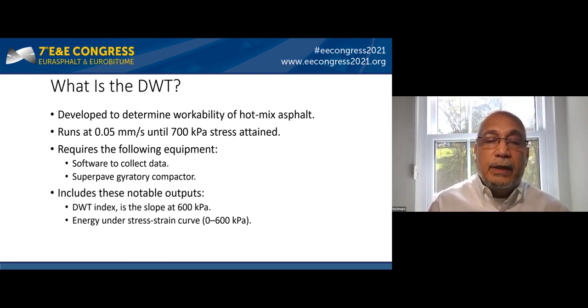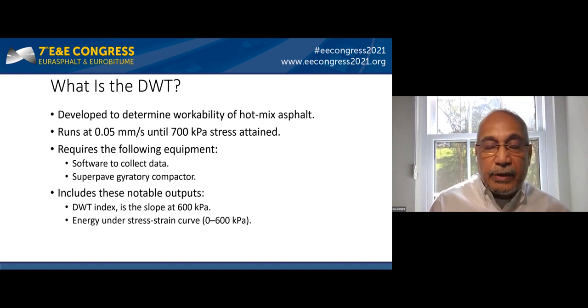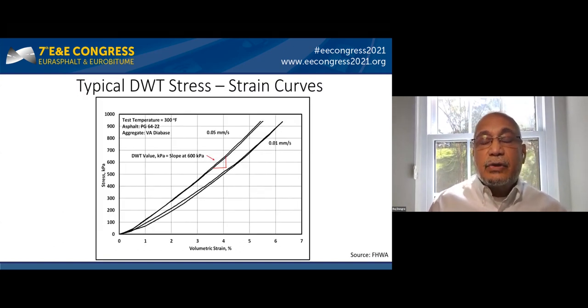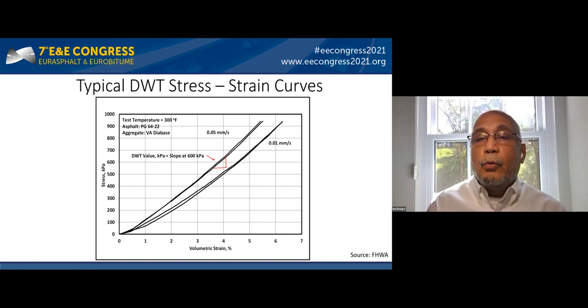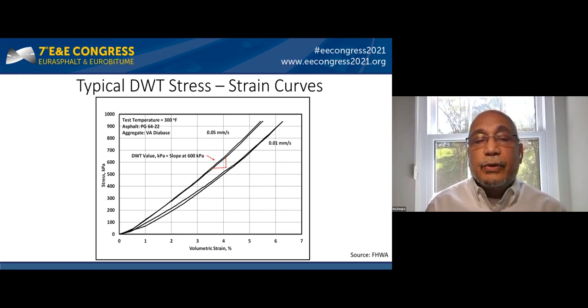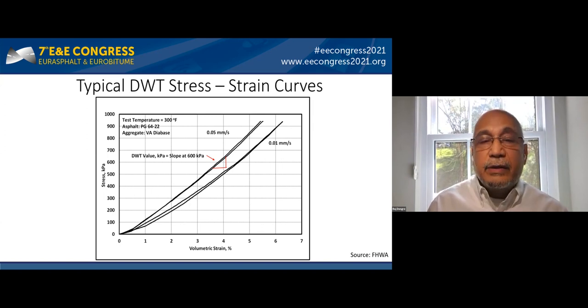No special equipment is required — only updated software if you own the SuperPave Gyratory Compactor. In the United States, exclusively the SuperPave Gyratory Compactor is used, and the test was developed so that after it is conducted, you can use the same sample and proceed with compacting a mix design sample of 115 mm height, saving time and material. The outputs from the DWT are the DWT index — essentially a slope determined at 600 kPa stress level on the stress-strain curve — and the energy under the stress-strain curve.